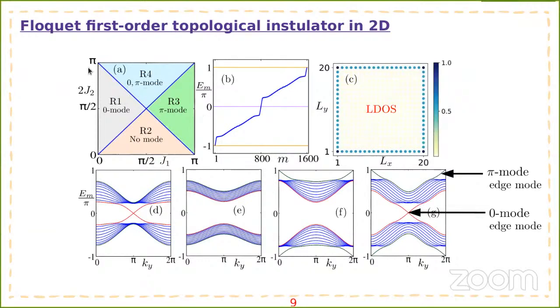So following our driving protocol, we can have this kind of phase diagram in J1, J2 parameter space, which can be divided into 4 parts. In region 1, one can get only the 0 modes. In region 2, there are no modes. Region 3, only pi modes, and in region 4, one can get both 0 and pi modes. So I will focus only on region 4 here.